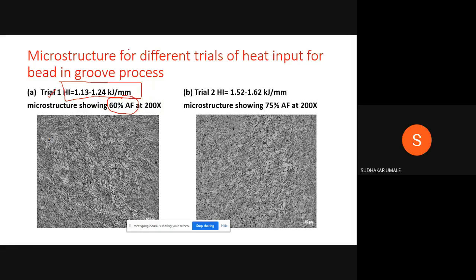Now, just observe my second trial. I have changed my current, voltage, and speed. During that period, this is my heat input, which is larger. What I am getting there is 75%. Now this is increasing, larger than this. And just observe that, I got this needle-like structure.